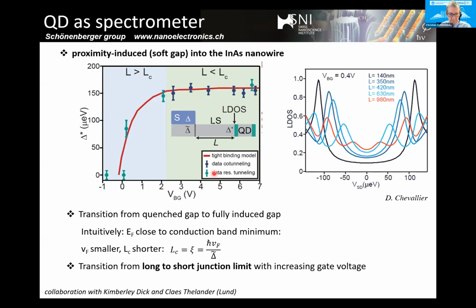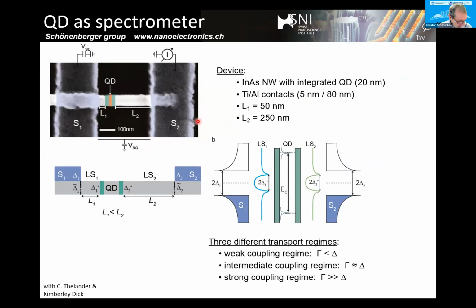And the understanding of this is very simple, because if you change the backgate voltage, your Fermi level goes up. If you're just above the conduction band minimum, you have a very low carrier density, and the Fermi velocity is then very low. If the Fermi velocity is very small, the coherence length is short, and the physical length of the wire is longer than the coherence length, and then you are essentially in the long junction limit, where Andreev bound states can fill the gap, so eventually you don't see a gap at all. Then all of a sudden it comes up, and in this region there is essentially only a pair of Andreev bound states left, which is pushed to the gap edge, and that's why we see an apparent gap which is very close to the aluminum gap. It doesn't explain why it's soft, but it explains this sharp onset, and this can also be simulated quite well by theory. Now let me go over the last 2 minutes to this sample.